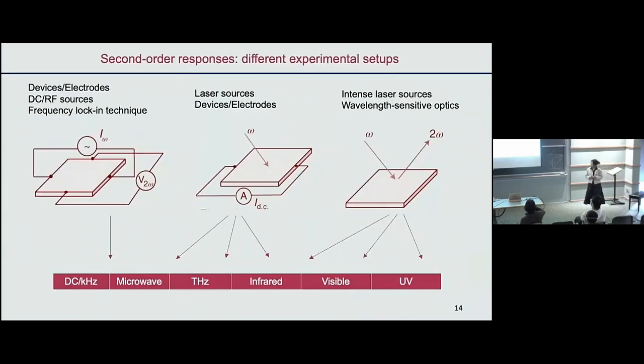So I just want to broaden it a little bit to put this kind of measurement in context. This photocurrent measurement is a nonlinear, second order response, because the excitation is at frequency omega, but the response is at DC, essentially zero, right? It's similar to optical SHG, for which I think the previous speaker in the morning talked about the importance of these measurements, right? Actually they share the same kind of symmetry arguments, and they can detect the same symmetry properties of the material.